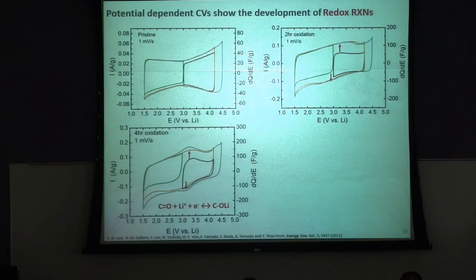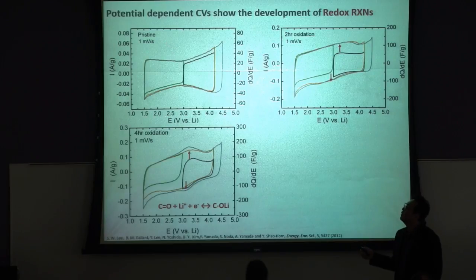Then, if we measure the electrochemical characteristics of these carbon nanotubes, this is the pristine carbon nanotube. We measured cyclic voltammetry from 1.5 to 4.5 V, since we use this for a cathode or positive electrode. It shows almost a box-like shape, basically a potential-independent current response. This is a characteristic of double layer capacitance.